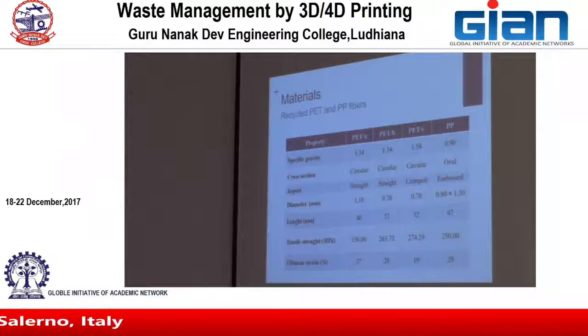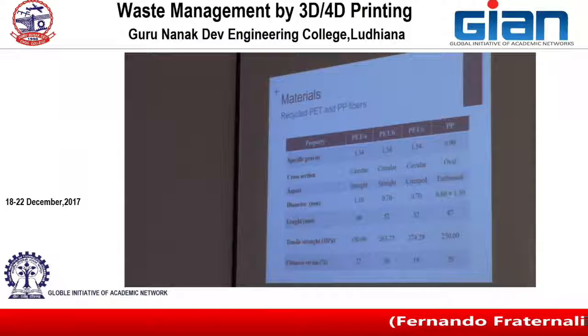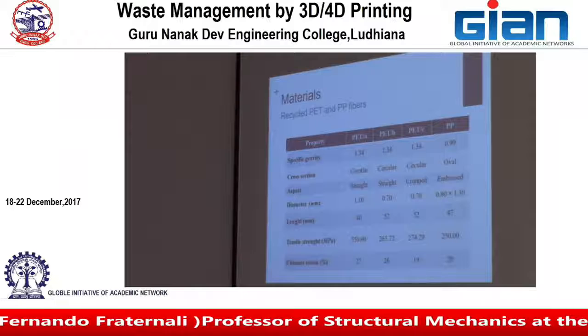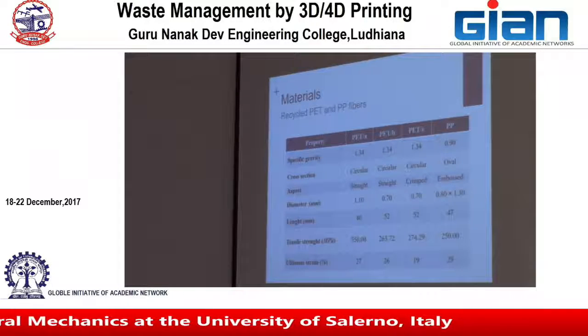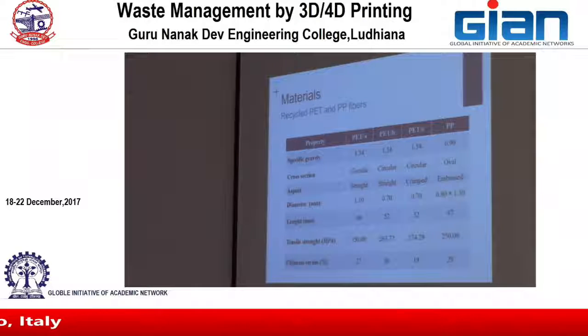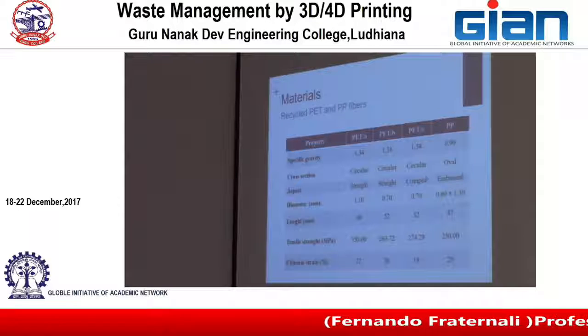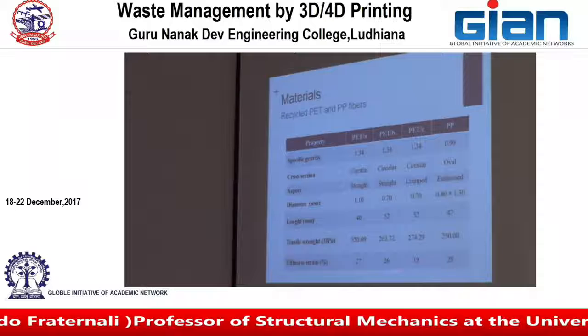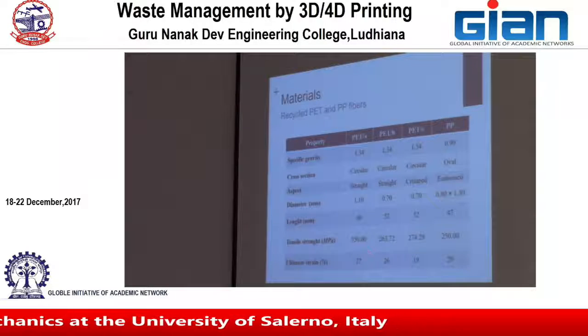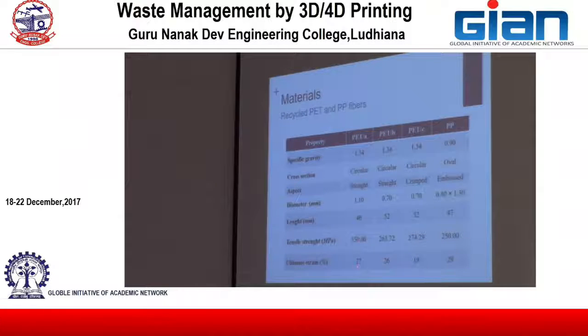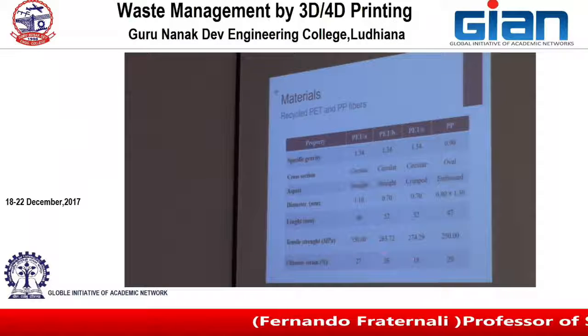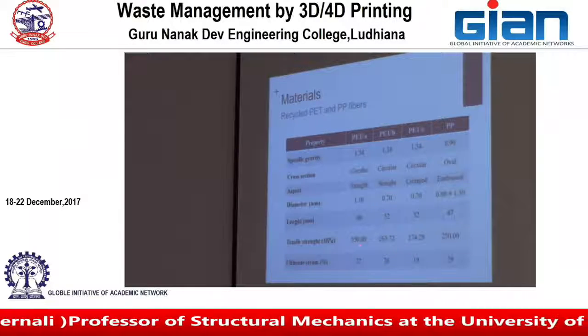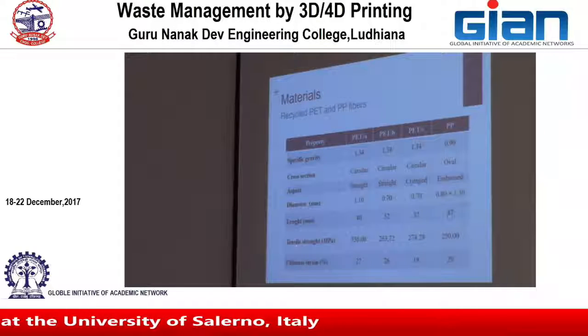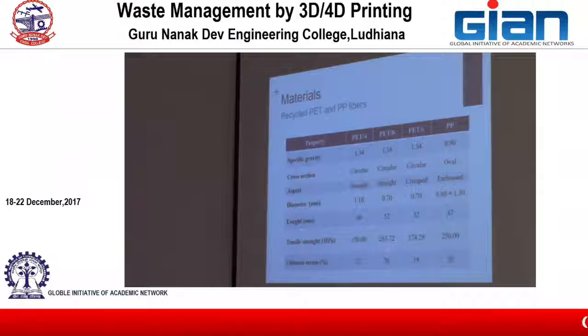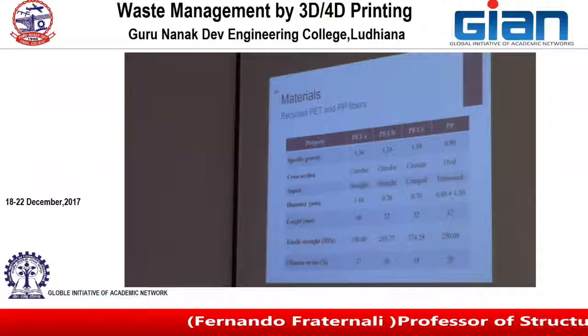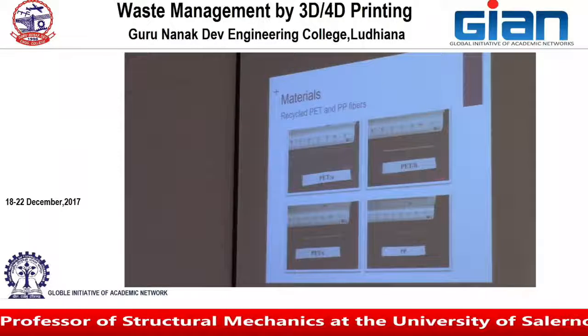During the extrusion process, you can modify the mechanical properties of the material through some pre-straining of the wires. So by applying some pre-straining, you can vary the mechanical properties. And so we had several fibers with different mechanical properties and with different ultimate strain. There was a first kind, high strength fiber, and the second kind was instead with a lower tensile strength, but similar ultimate strain. So those were the fibers that we examined.